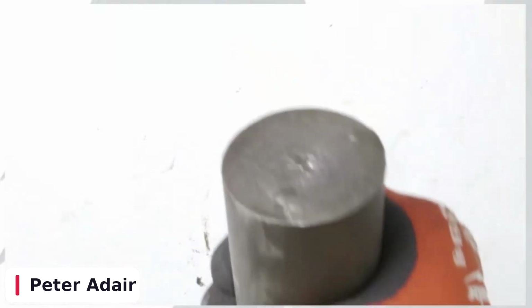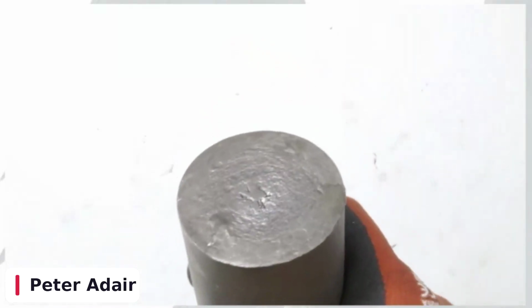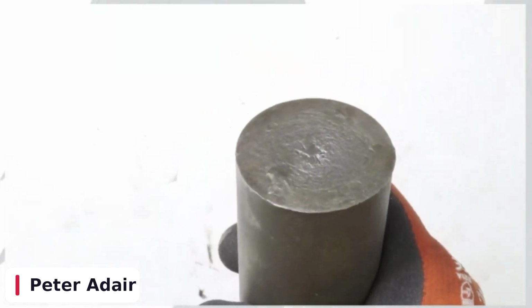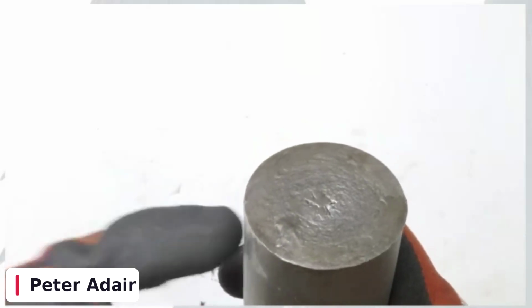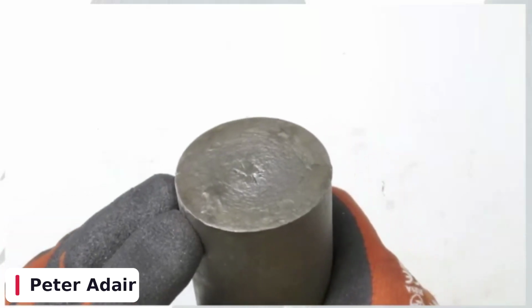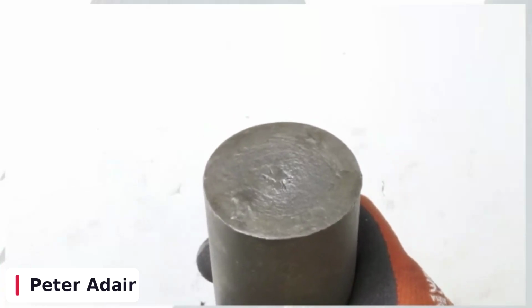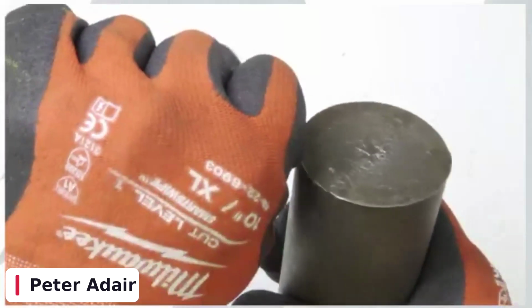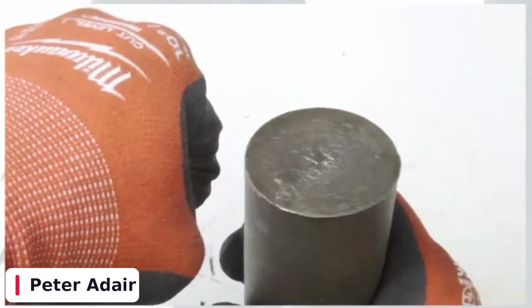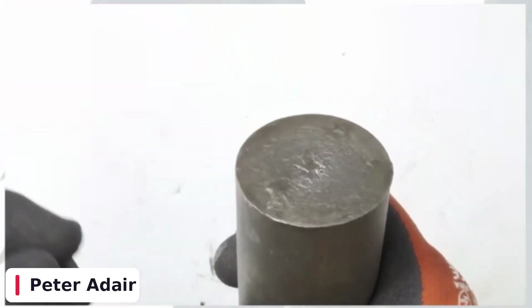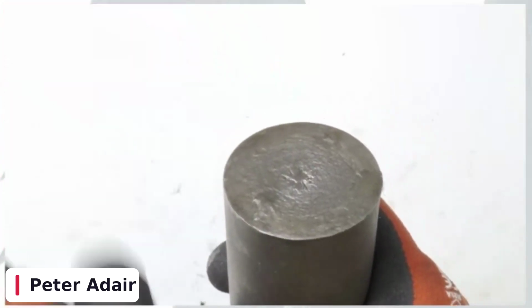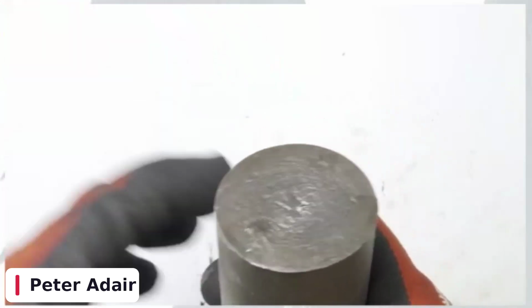All right, so the torsional tensile shear is a similar break, but you can see there's no 45 on this. This is a straight 90-degree break. This is a hit so hard, so quick that the shaft never had time to rotate up and spin into place. It just snapped it. Didn't have any time to load or properly twist that shaft up like a barber pole.